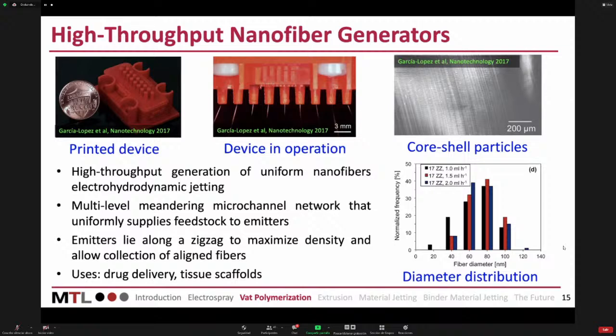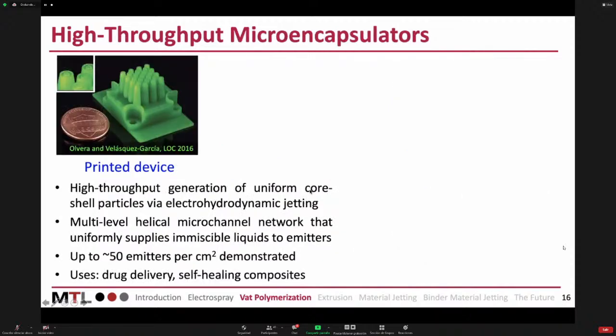And that's a problem because if you have, let's say, a filter that has holes of 1 micron and holes of 1 millimeter, well, that's really a filter for 1 millimeter, because the 1 micron particles are going to escape through the 1 millimeter. So you want as compact a distribution as possible. And what you see here is that even though we vary twice the value of the flow rate, you get basically the same statistical distribution, which is what this development is about: high throughput production of nanostructures.